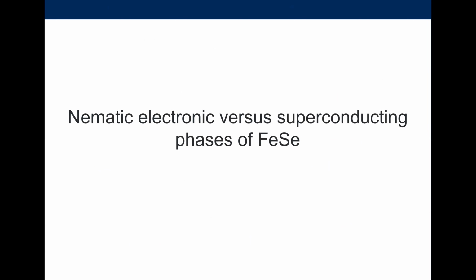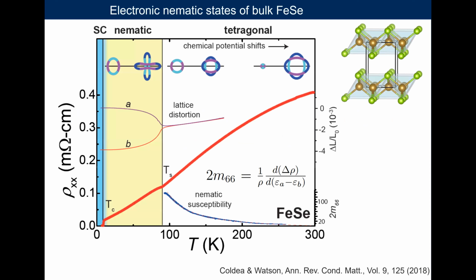Okay, so firstly, I will just show you some of the phase diagrams by varying other parameters in iron selenium. Actually, before that, how is the behavior of the system as a function of temperature? Looking at its resistivity, first of all, we have quite a bad metal at room temperature. It goes through this transition, TS, and then it's almost linear resistivity before it enters the superconducting phase.